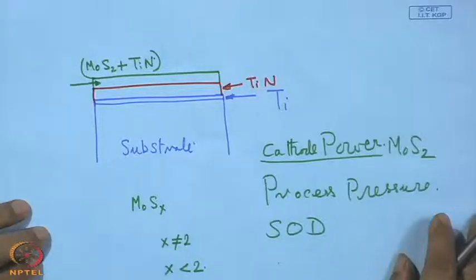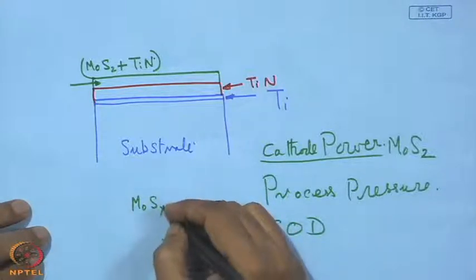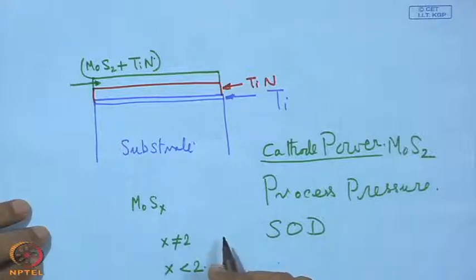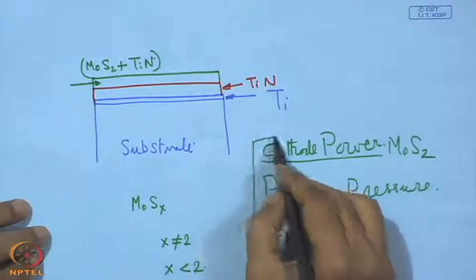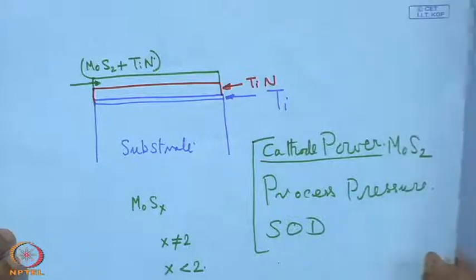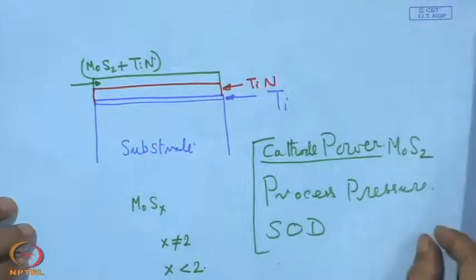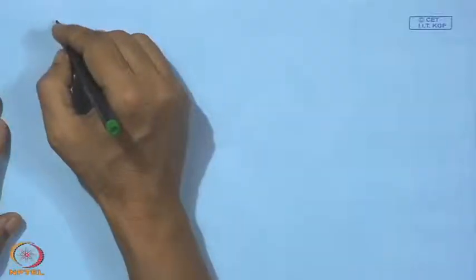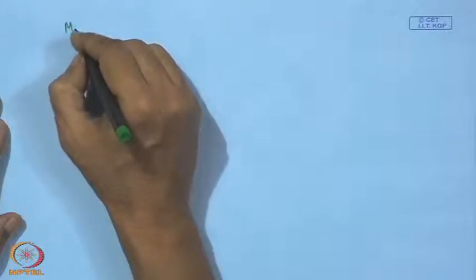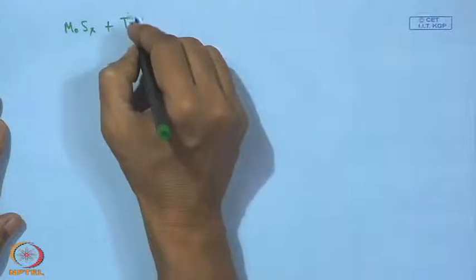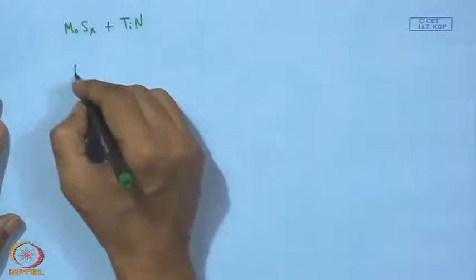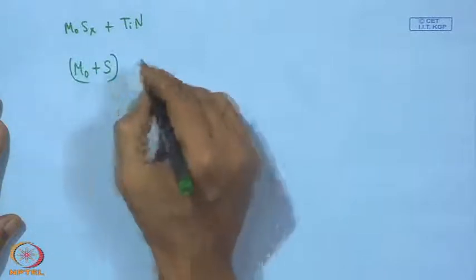So, it is actually more reasonable to write MoSx instead of MoS2, where this x value would depend upon the cathode power, process pressure and SOD under a given set of conditions. So, this is MoSx coating, presenting this in the general form MoSx. Now, with this MoSx and TiN, the most important thing here is what will be this proportion, the atomic percentage, that means MoSx plus TiN. So, one would be interested to know what will be this Mo plus S within this TiN.